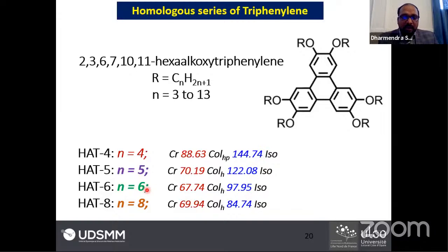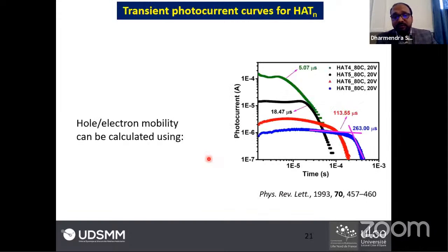reduces. Okay, so molecular ordering can also be changed, so charge transport property and mobility values are also changed. Here we have shown you the photocurrent curves for the HAT4, 5, 6, and 8. You can see here we can obtain very good transient photocurrent curves. By estimating the transit time, we calculate the hole or electron mobility using this formula.